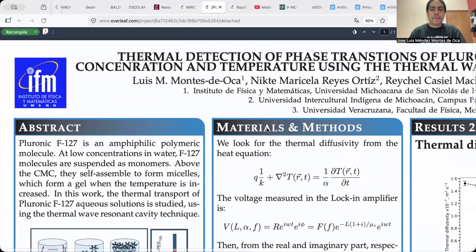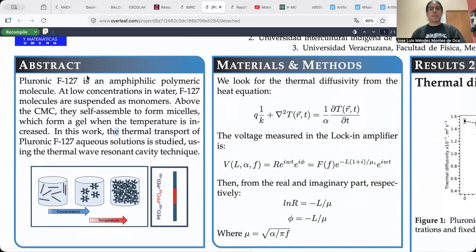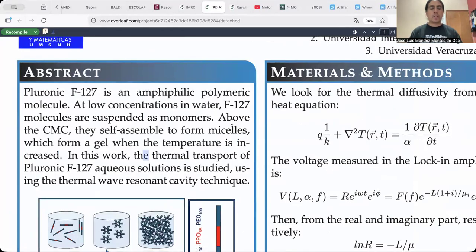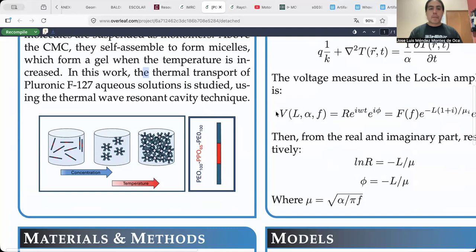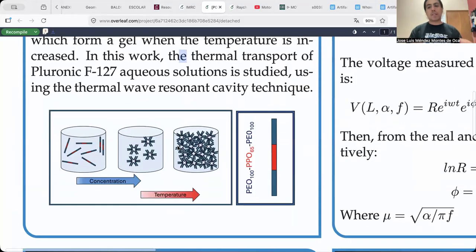Well, the Pluronic F-127 hydrogels are made of polymeric amphiphilic molecules, which at low concentrations remain as monomers in solution in water, and as the concentration is increased, they start to form micelles as a configuration of low energy. And if the temperature is increased, those micelles start to entangle to form a rigid gel.